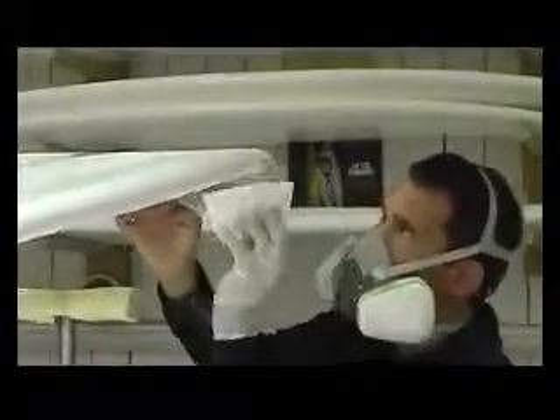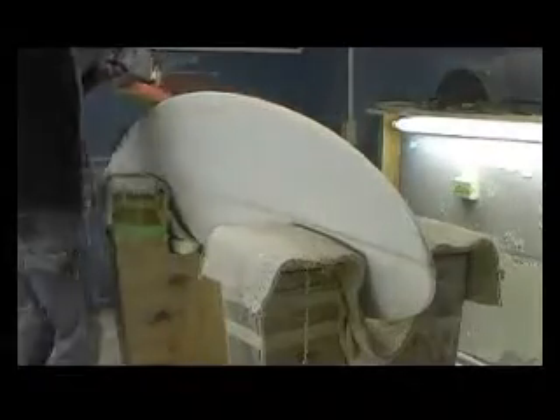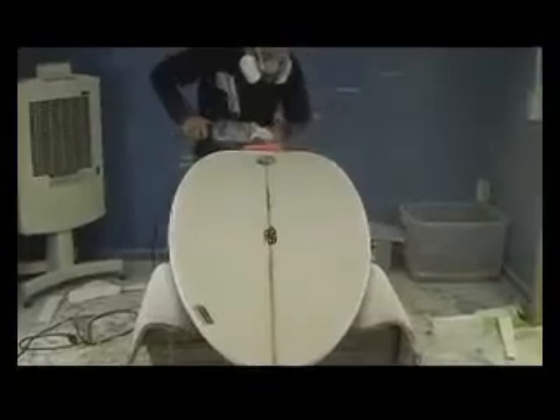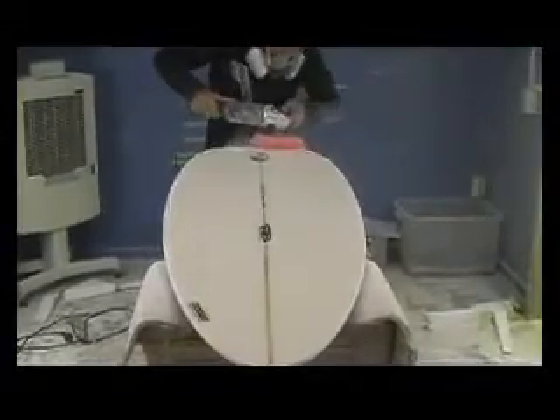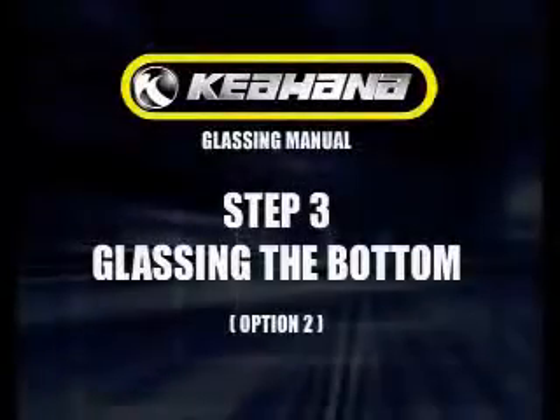Let the board dry. Sand the laps flat. Also sand around the rails and about 4 inches into the bottom to create a stronger bond between the dry resin on the bottom and the wet resin from the deck. This will avoid any future delamination. Option 2.